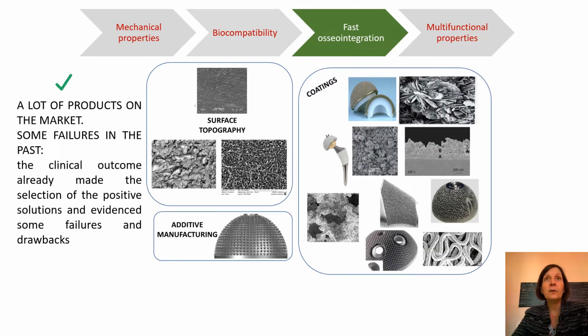And then the second requirement was fast osseointegration. At the moment there are a lot of products on the market responding well to this requirement, so with good osseointegration, obviously depending on the type of the bone where the implant is. And some failures occurred in the past. You can see here an overview of different surface topographies produced by different techniques, such as additive manufacturing or different coatings. In some cases we had some failures, like in the case of the sintered wires, but there are a lot of good choices on the market. So this is not such a big issue at the moment.